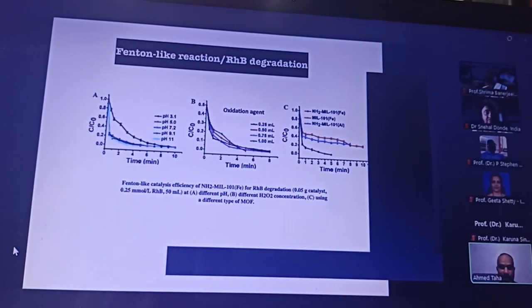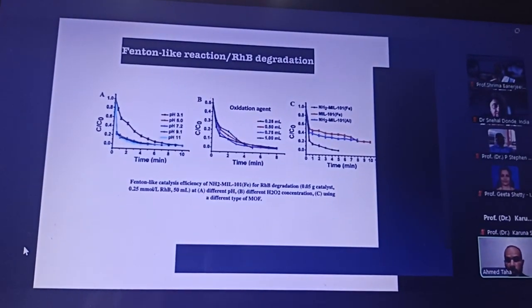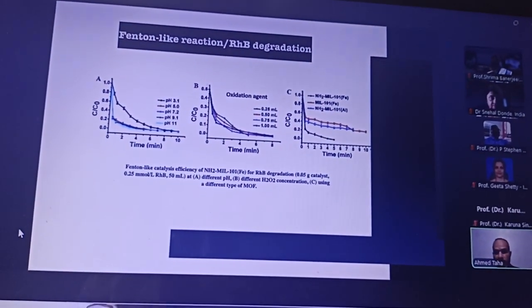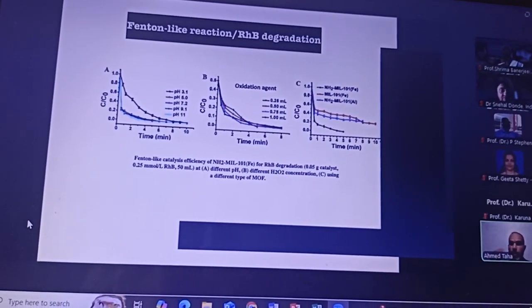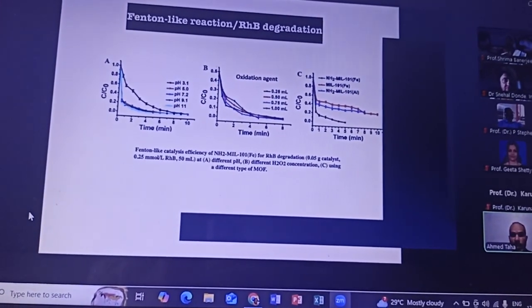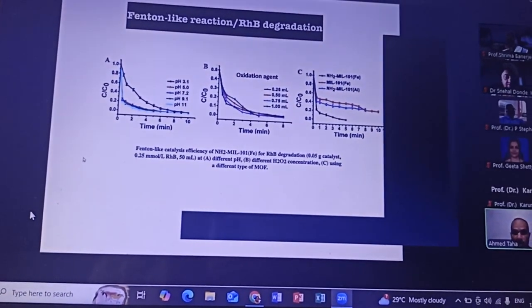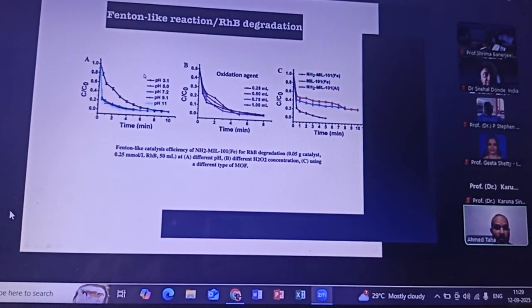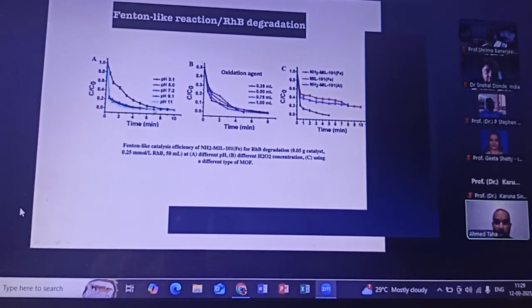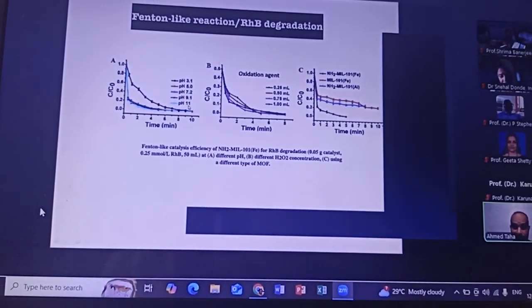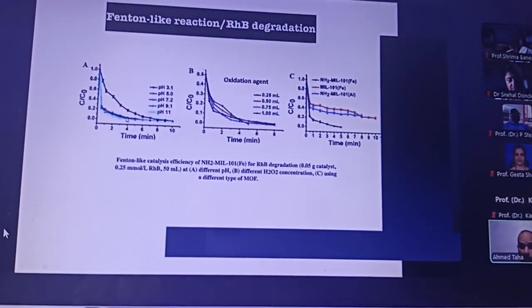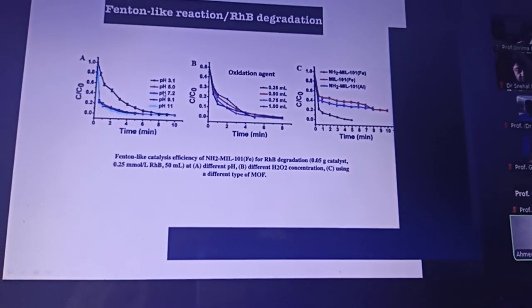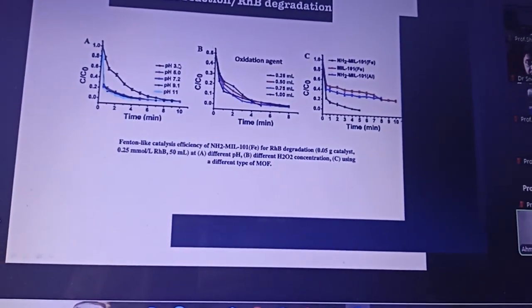So we then started to do the Fenton reaction. We added our material, we added the H2O2, and then we measured the performance at different pHs. As you see, the material can work fine even in a very alkaline pH, which is one important achievement, which now we can tackle the problem of limited pH to 3.1 of the traditional Fenton.